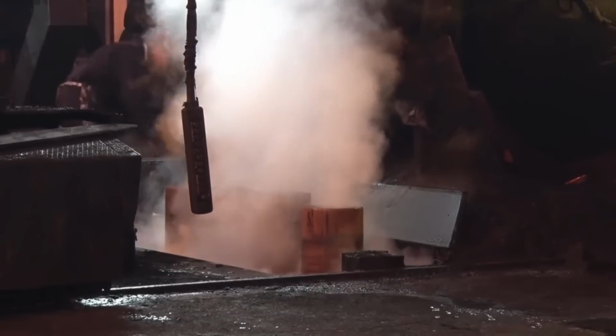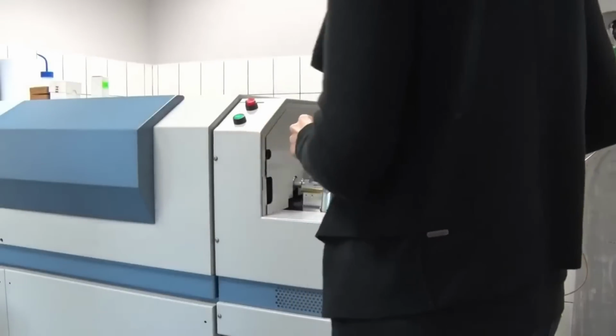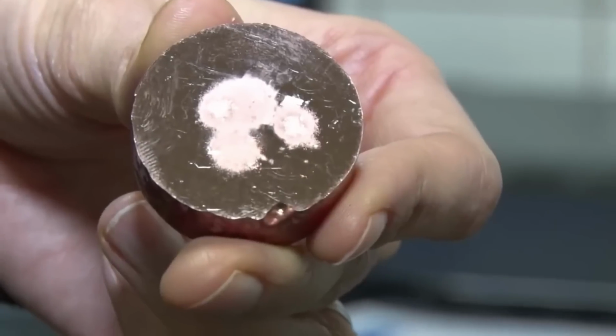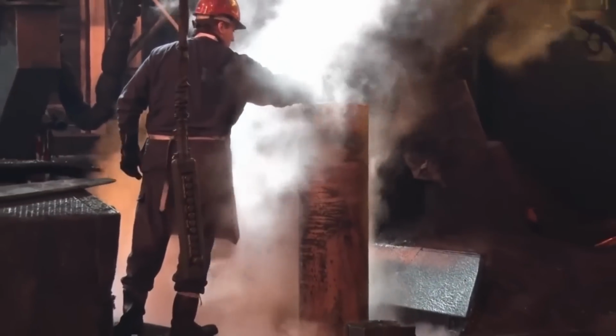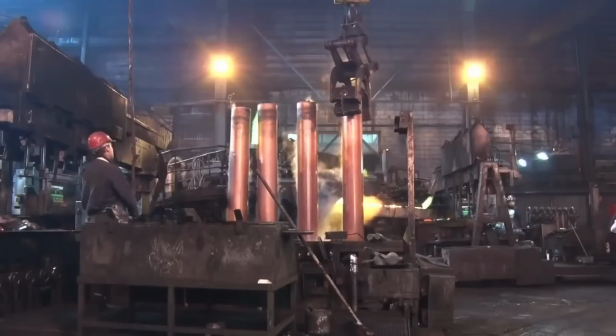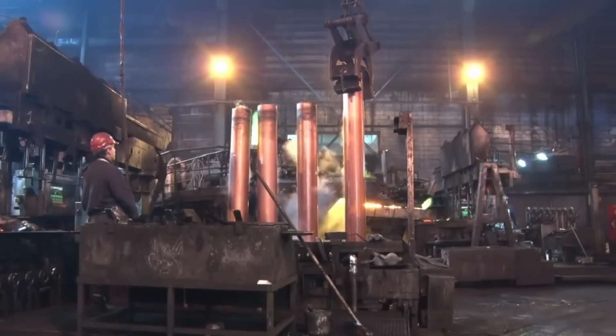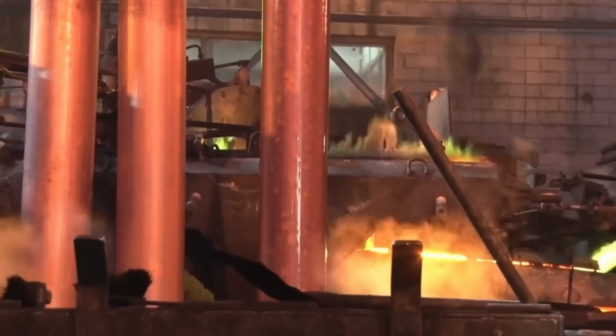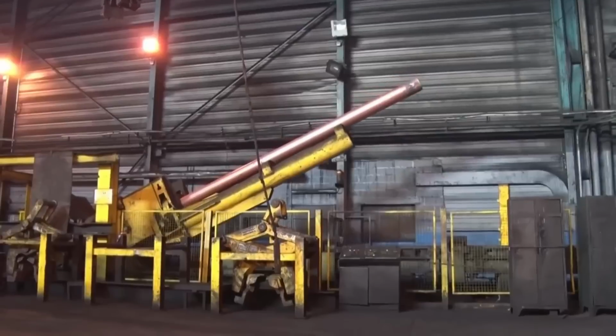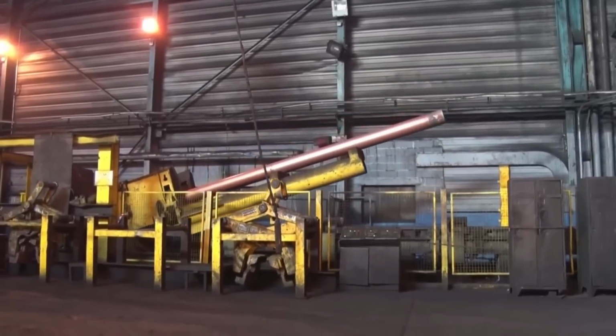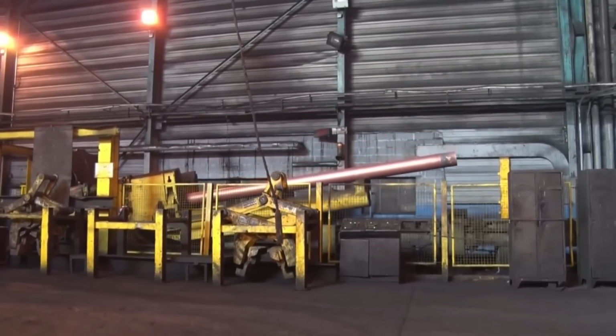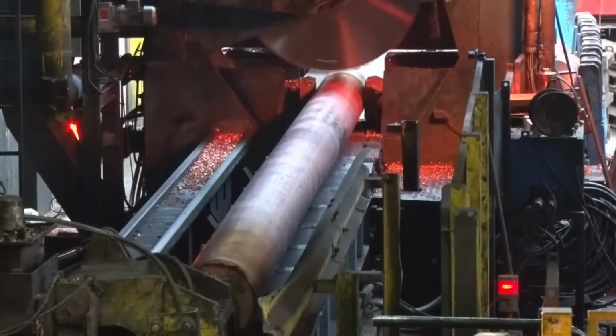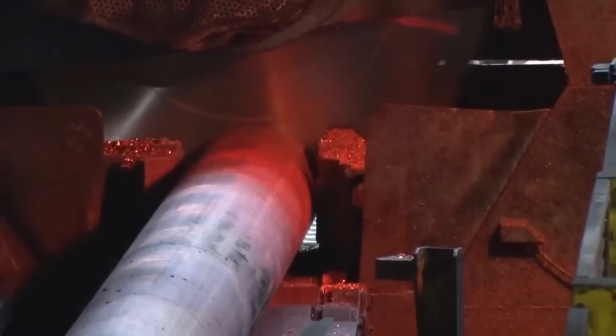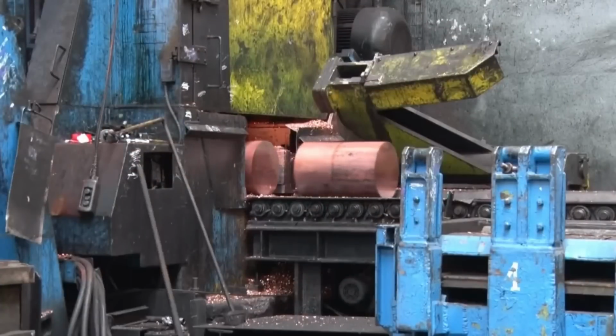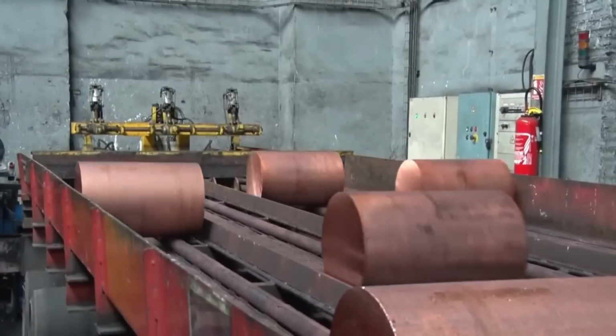Water circulation is employed to cool the metal rapidly, resulting in solidification. The chemical composition of the copper is checked before each casting, and once the billets are fully cooled, they are extracted from the mold. The extracted billets, weighing approximately 450 kilograms each, undergo several transformation processes. First, they are heated to around 850 degrees Celsius and introduced into the container of a hydraulic press.